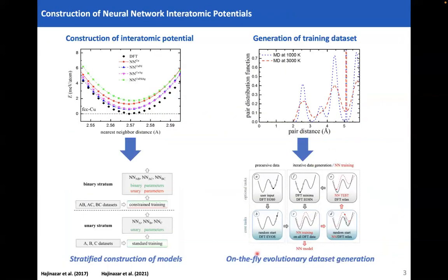The workflow that I described here, which is an automated package to generate the model, includes elevated pressures. So you set up a desired range of pressures and generate the data at each pressure. And in most of the examples that I showed, the machine learning models used included higher pressure data as well on top of the zero GPa data.